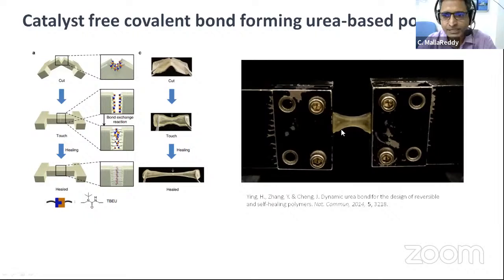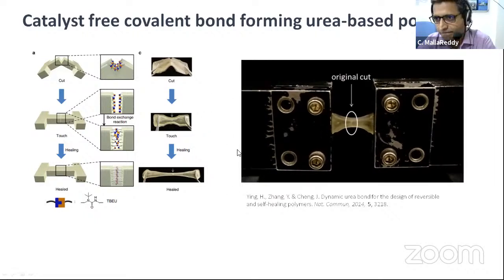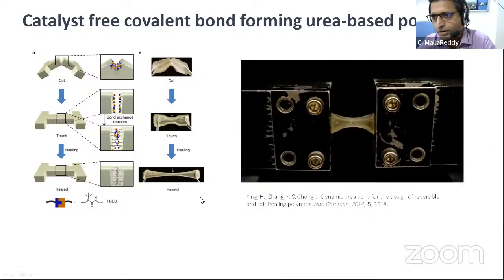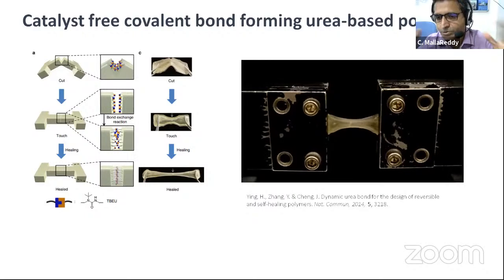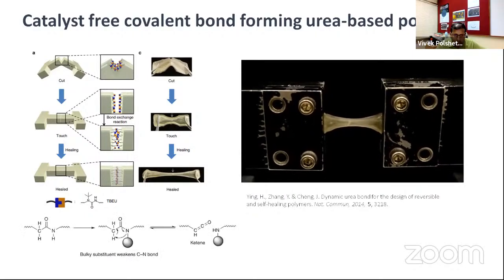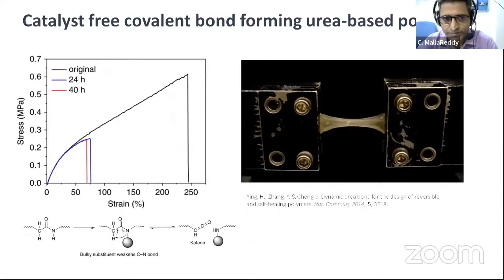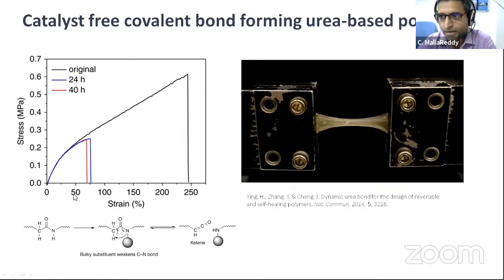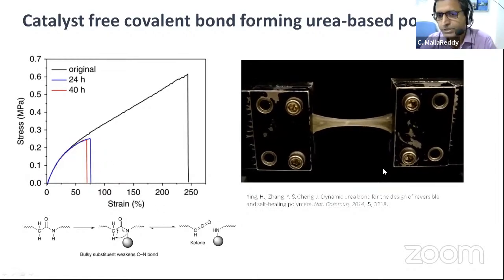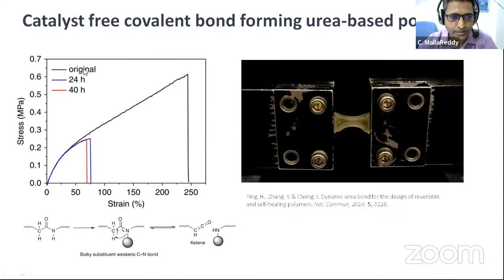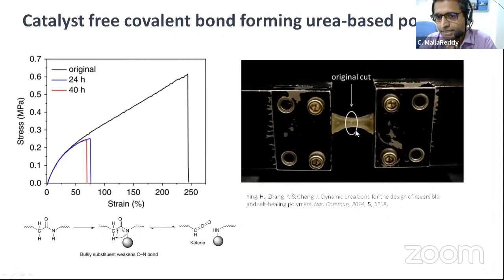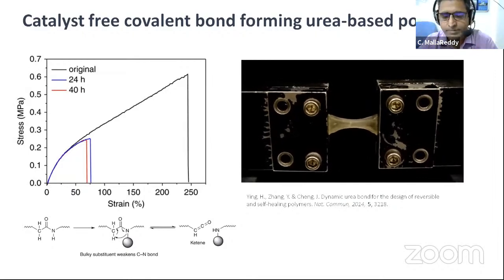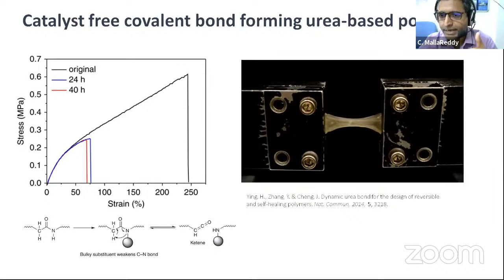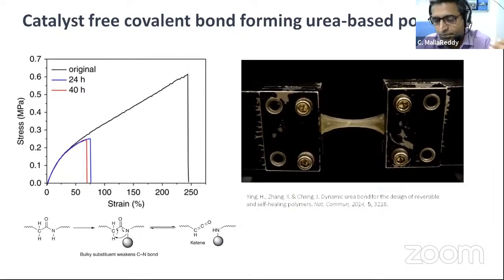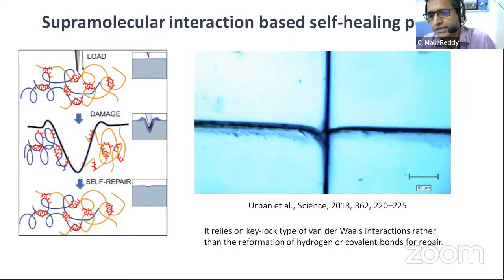Yeah. So here again, if you see, this is a very soft material, and most of these materials are very soft, either like gels or elastomers. You can stretch them. So achieving self-healing in very hard materials has been very, very difficult so far, and not many people have achieved it. Even after self-healing, your healing percentages are not very large most of the time, or you need to heat them or put them together for 24 hours or sometimes 40 hours. Then you have some healing. So it takes time, and most of the time it happens only in the softer materials. You need diffusion inside the material, or sometimes you need to also heat, or put them under light, or give some stimuli. So that is the difficulty, and people always try to achieve it without any external direction.